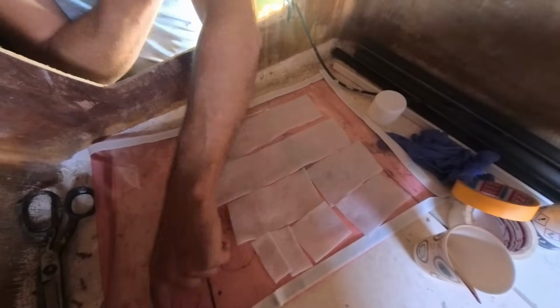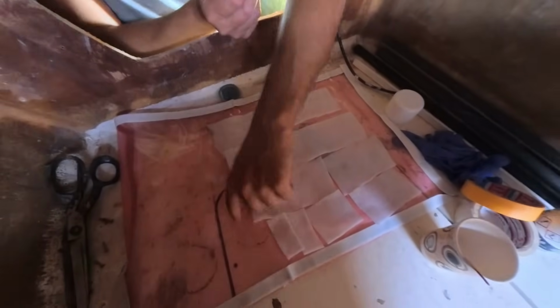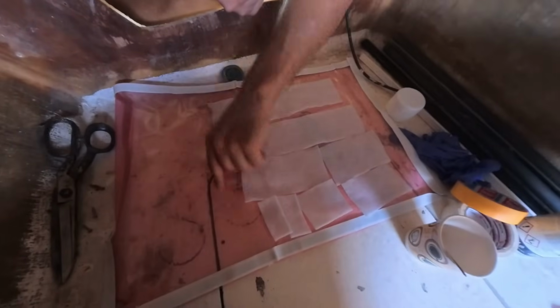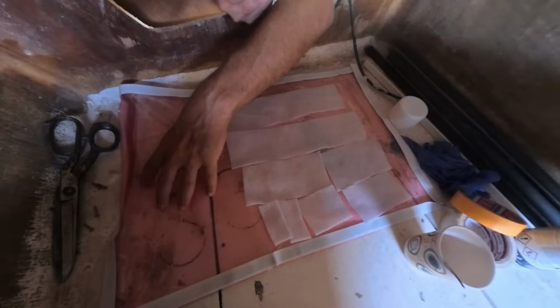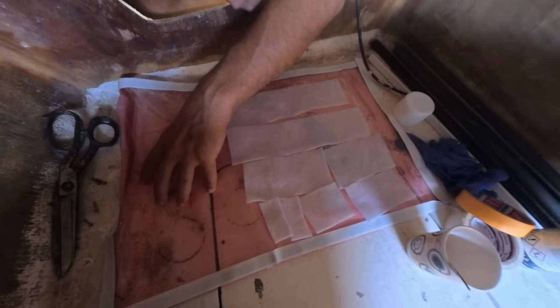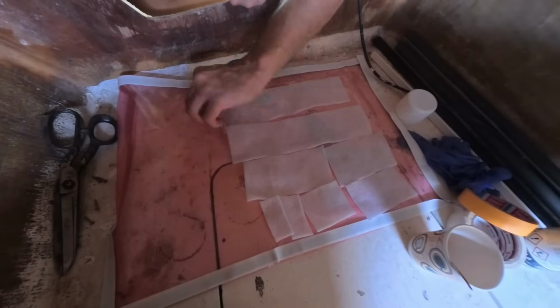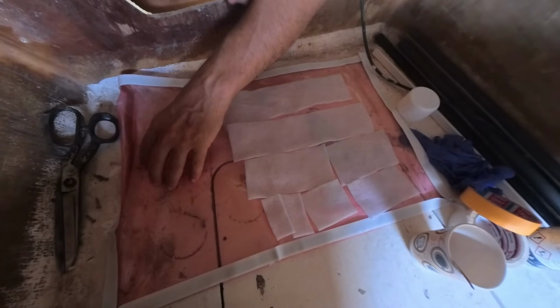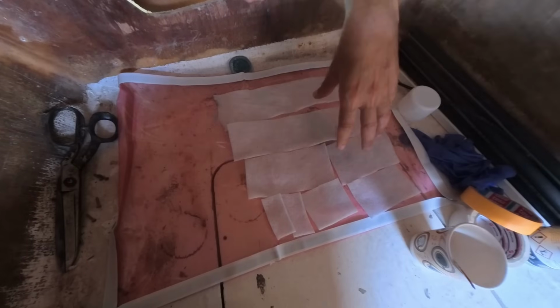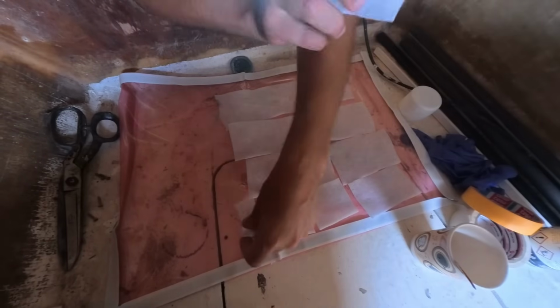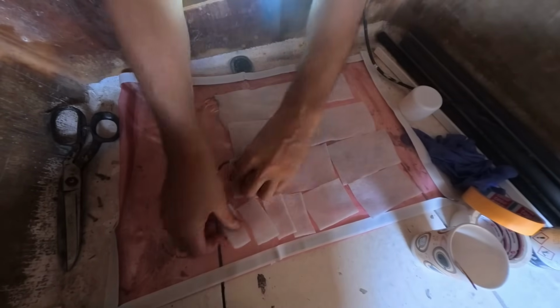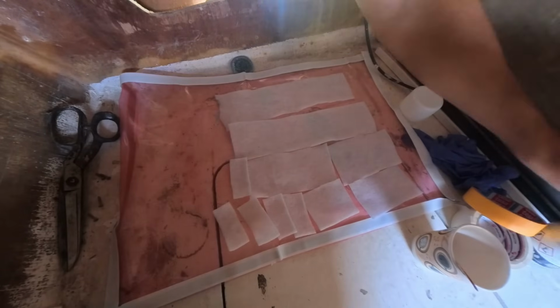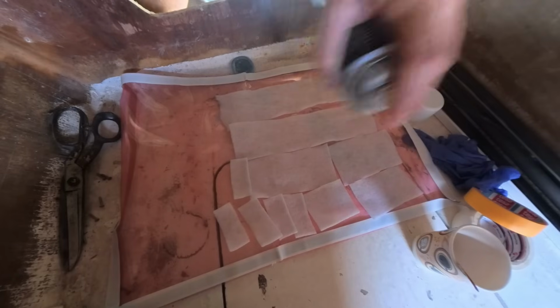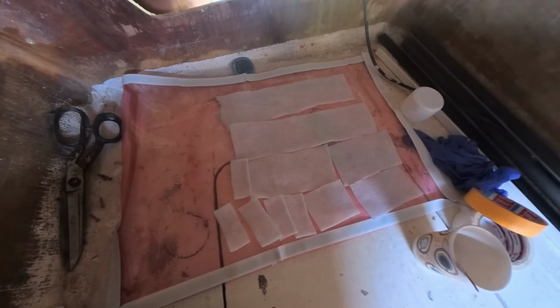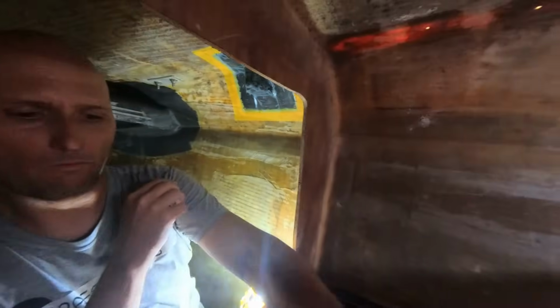Where there's no breather felt over this side, if this seals, particularly on wet resin, it means that whatever air is here is essentially trapped, because the bag will create a seal with the wet resin here and not let the air suck out. So the breather felt is really important to allow the air that's inside the bag in particular to move around and be sucked out by your vacuum pump.